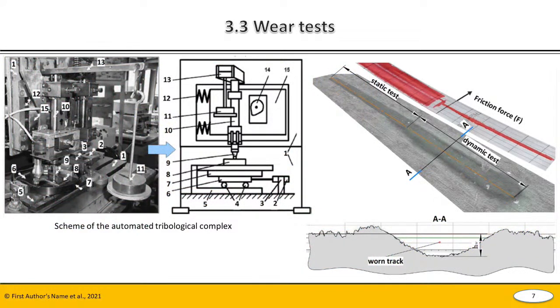Then the hardened specimens were tested in both quasi-static and dynamic loading wear conditions. The quasi-static tests were performed by reciprocating sliding of a hard metal spherical counterbody with a frequency of 1 Hz along a track of 4 millimeters at a constant load of 30 Newton. In the dynamic conditions, the wear tests were implemented with an additional dynamic load applied in a sinusoidal way with a frequency of 25 Hz. Next slide, please.